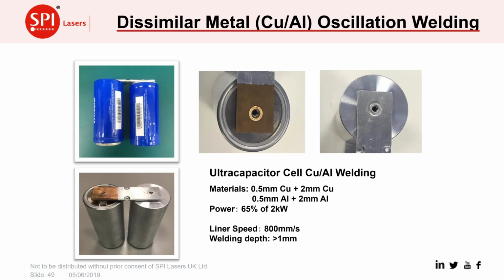Another area is capacitors, the ultracapacitors. Again, we're looking here at some dissimilar metal welding that's been able to be done at reasonably high speed with less than the full power from the 2 kW laser here. So we've got welding copper and aluminium together for these high performance capacitors. The oscillation welding is there. Again, you can see that we've used the circular pattern around the contactor there. And again, this is one of the reasons why the circular oscillation pattern is important, because as you weld a circular conduction weld, you've got a good uniformity as you go around the weld in whatever direction the linear speed is pointing in.